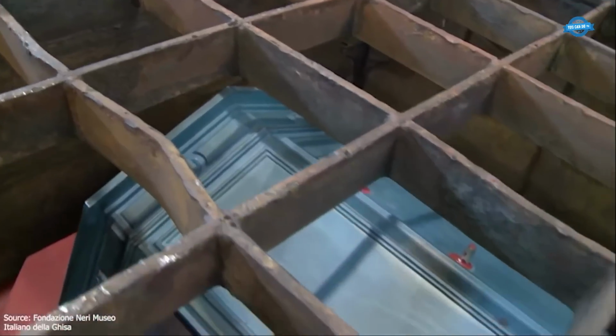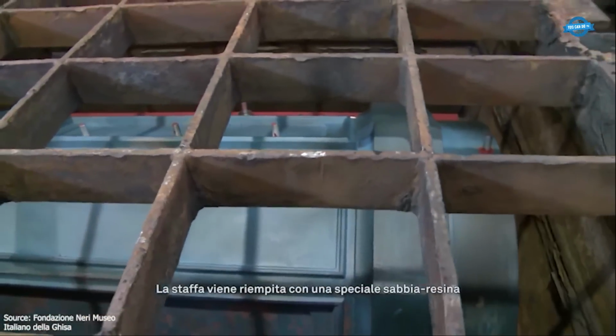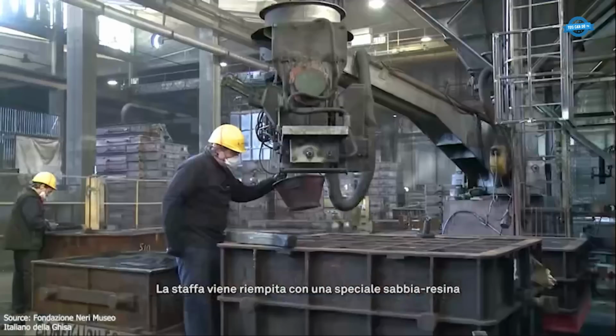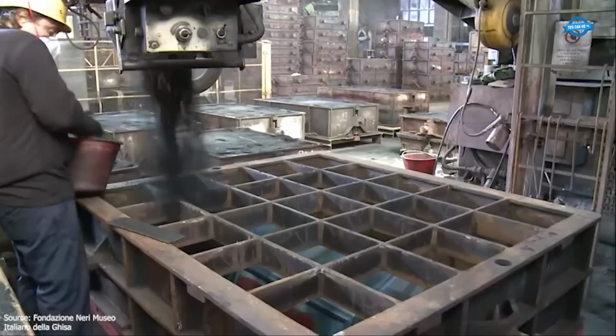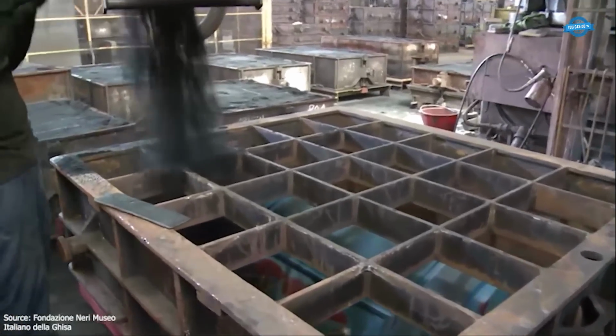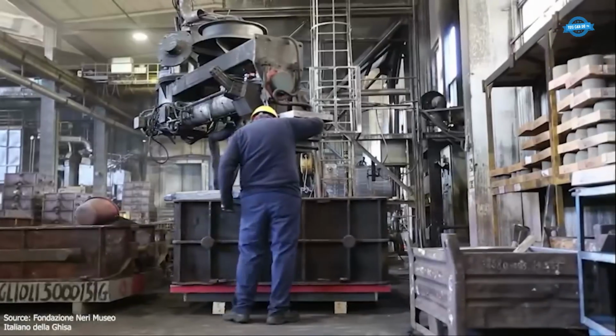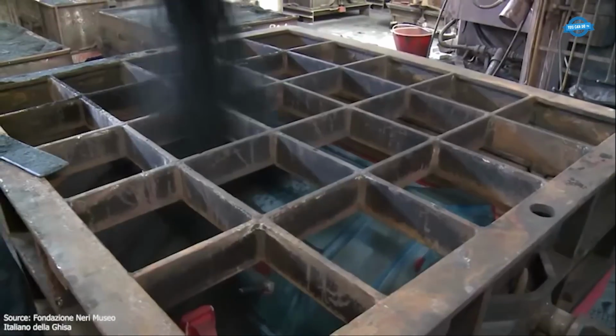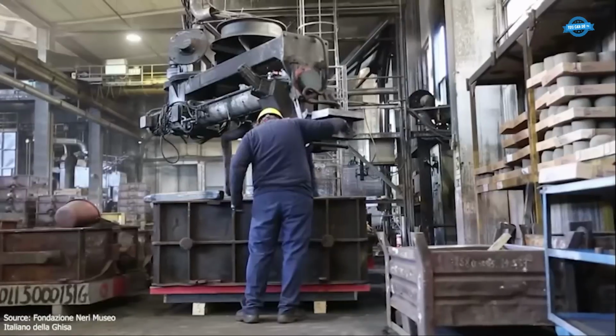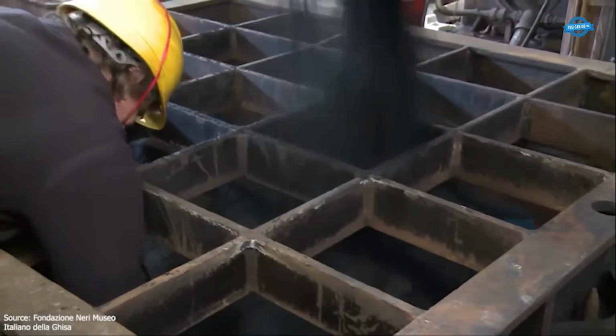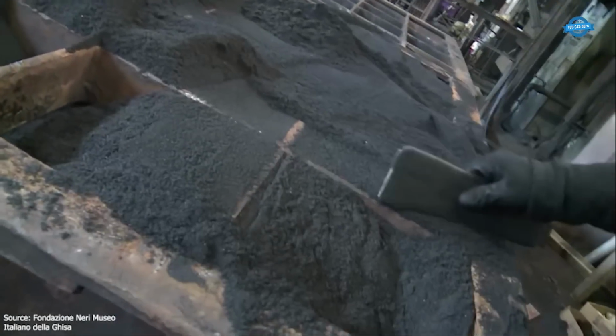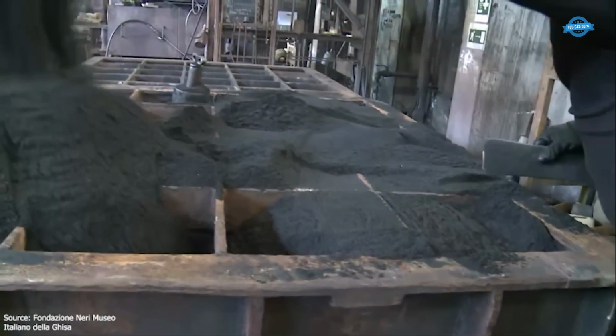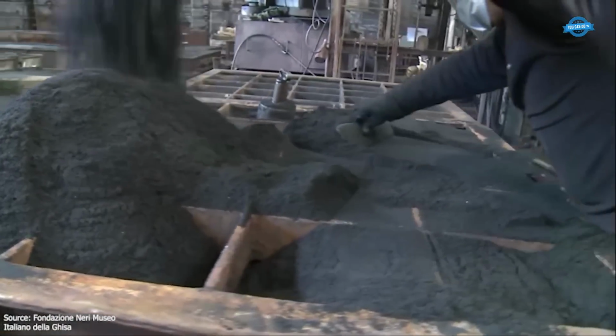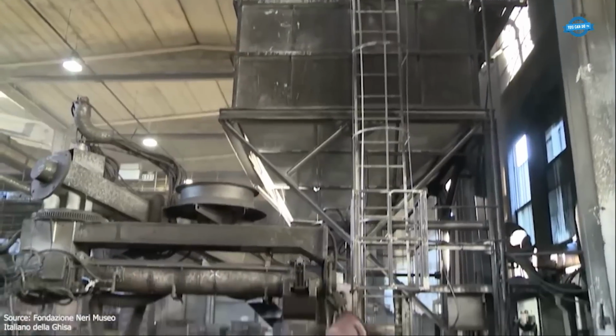the imprint. Once prepared, the model is placed inside a large steel molding box. This box is then filled with a specially formulated resin-bonded sand. As the sand hardens, it captures the precise shape and contours of the model. The operators also press the name of the client into the surface of the sand, providing a means of identification for the mold. The sand requires approximately 10 minutes to fully cure and harden.